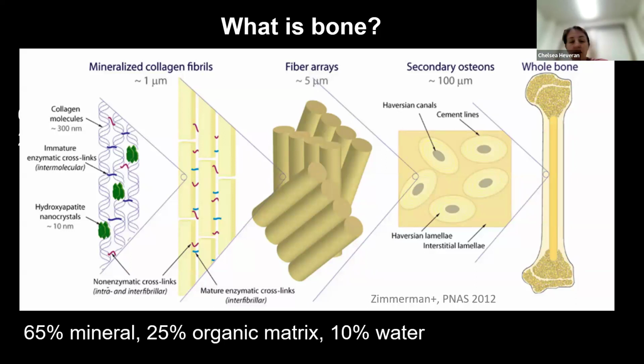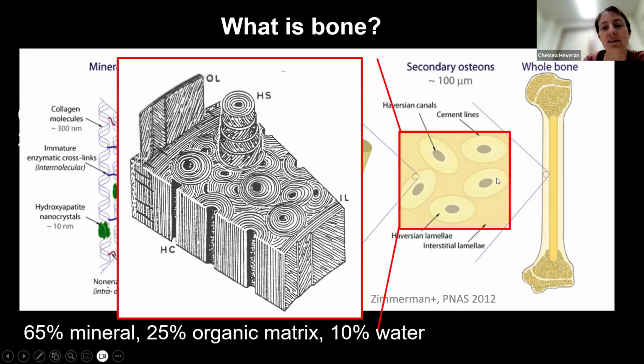Bone is about 65% mineral, and the rest of it's organic. It's actually impressively hydrated as well. So fibrils of collagen and mineral assemble as fibers. These fibers are further stiffened by crosslinks, and these mineralized fibers pack in oriented sheets. And these sheets roll up in osteons within the dense part of cortical bone. What that looks like is that you almost have these sheets of twisted plywood. And so bone has some incredible microarchitecture to it.